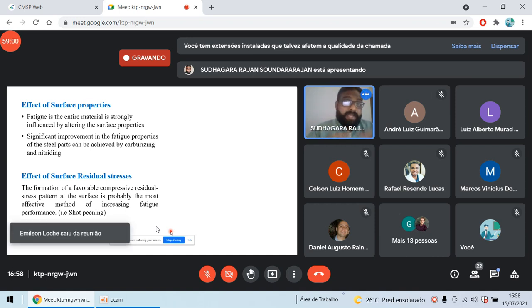At the same time, if we have a compressive residual stress in the surface, what will happen? If we superimpose a compressive residual stress on the surface service load, then there will be a reduction in the stress and you will get a prolonged life. That's all, as simple as it is. That's how the surface residual stress influences the fatigue life of the material.